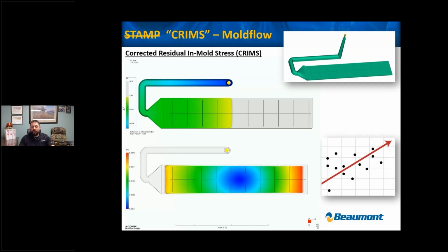So essentially, if you're not familiar with a regression analysis, it's just a mathematical method of sorting data. So we're defining independent and dependent variables, and we're fitting those variables to a curve to understand the CAD nominal value to post shrinkage values, and then also comparing back to Moldflow. Then finally, step 7, the measured values are inputted into the simulation properties tab within the material UDB file.